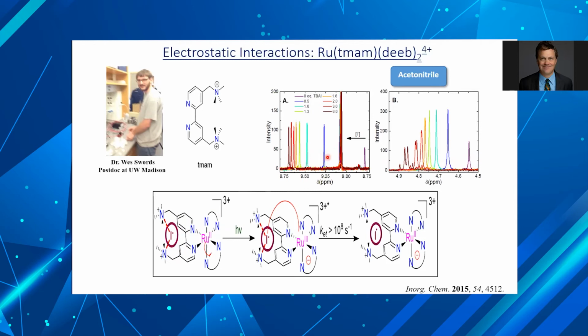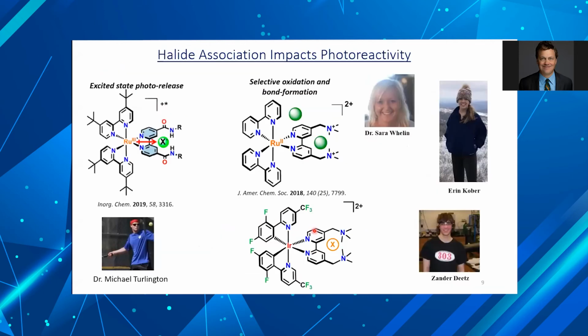These are the interactions with the methylene carbons on the TMAM ligand, these hydrogens here. And this shift in A is what happens to the 3,3' hydrogens. So it formed a little pocket there. And by tuning the energetics with iodide, he could see direct electron transfer at these interfaces. And he did successfully apply it to interfaces to show that this could promote energy conversion. We now have a team of people working on these kind of applications.